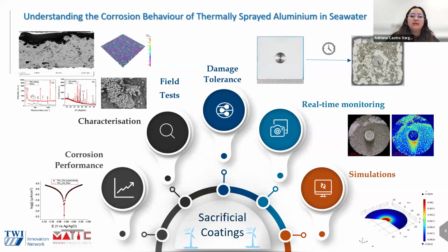But here you can see on the top the picture of the nature of the coatings. They have high porosity, also high roughness. So the aluminum is quite active in seawater, but also as it offers cathodic protection, we can get a formation of calcareous deposits. So also the characterization of those products is quite important in order to understand their mechanisms. Field tests are also quite interesting to see the damage tolerance of these coatings.